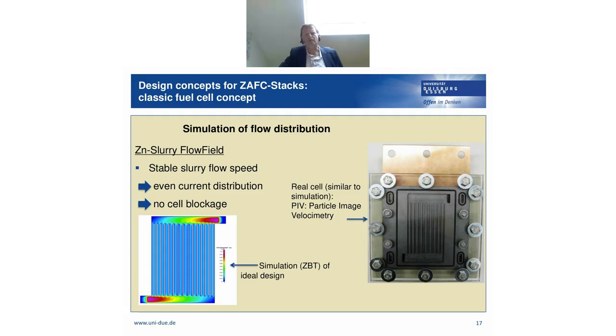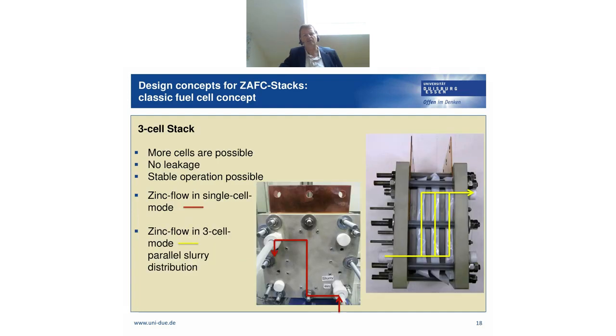We also studied the flow behavior with the help of the technique PIV, which is particle image velocimetry. And this means here one part, the cathodic part of the cell, is replaced just with a glass plate, and we pump a fluid, not our slurry, through the cell, and into this fluid we give seed particles. With the help of these seed particles and laser flashes, the movement of these particles through the flow field can be recorded by a camera. So for several geometries, we use the PIV technique.